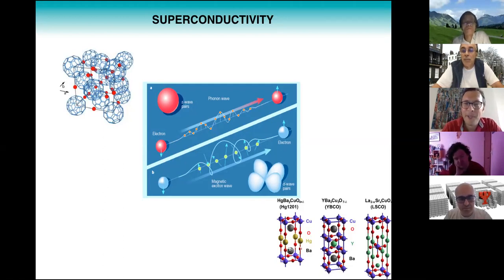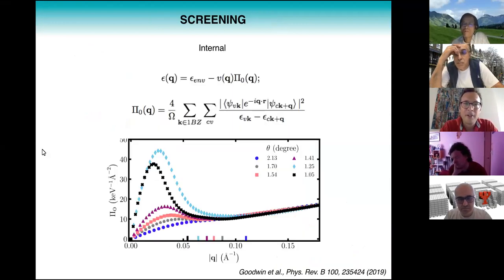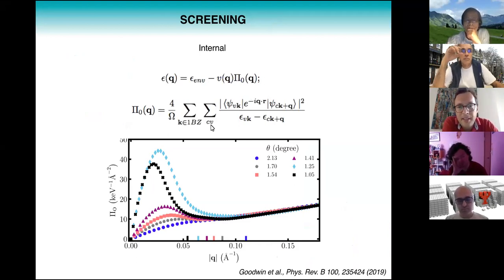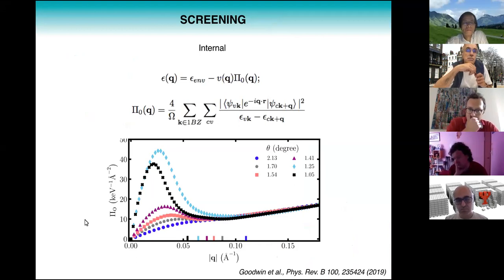We came across this mechanism more or less by accident, because we were studying internal screening. So far I've told you about the role of external screening, but of course the electrons within the graphene also have the ability to rearrange themselves. You can calculate this, and we did this using the random phase approximation. You calculate the dielectric constant, and to do that you have to calculate the polarizability, which is given as a sum of all transitions from occupied to unoccupied bands. Here I'm showing you the polarizability as a function of wave vector for 4 different twist angles.